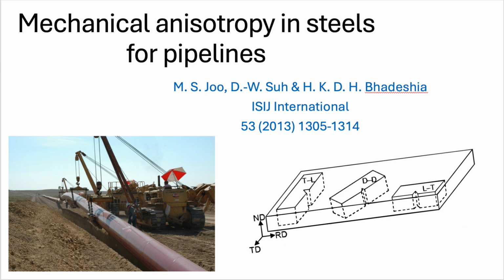It does, and that leads perfectly into a final thought, something provocative for you to consider based on what we've discussed. Lay it on us. Okay, so we noted that reducing carbon helps reduce perlite banding, making the steel potentially more isotropic, right? And modern high-strength steels generally have lower carbon contents anyway. So the question is, as metallurgists push for even stronger grades, think beyond X80 towards X100 or even higher, how much further can they go before the benefits of that raw strength are completely negated by the persistence of anisotropy? Will we hit a wall where increasing strength just doesn't help anymore because the directional weakness, maybe dominated by texture at that point, becomes the unavoidable failure mode?